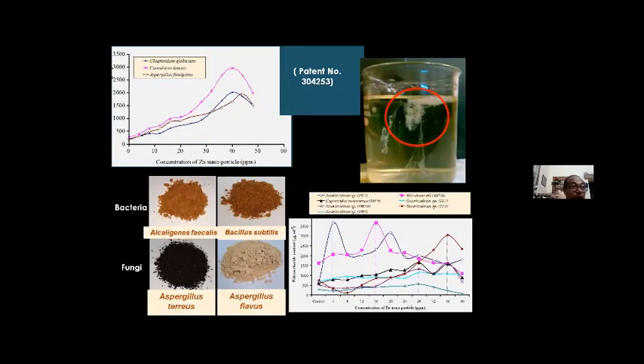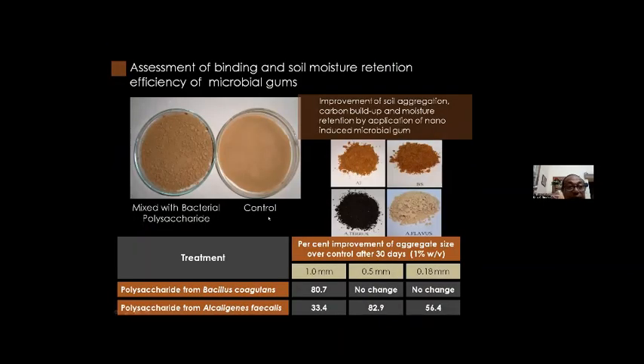Another very important point: the nanoparticle helps to improve polysaccharide production by polysaccharide producing organisms, polysaccharide producing fungi and bacteria. You can see here, we find 10 to 12 times more polysaccharide production with the application of different nanoparticles. We have developed a patented method, the polysaccharide powder making method. This polysaccharide powder, made from different organisms, we are using for soil aggregation, moisture retention, and carbon buildup.